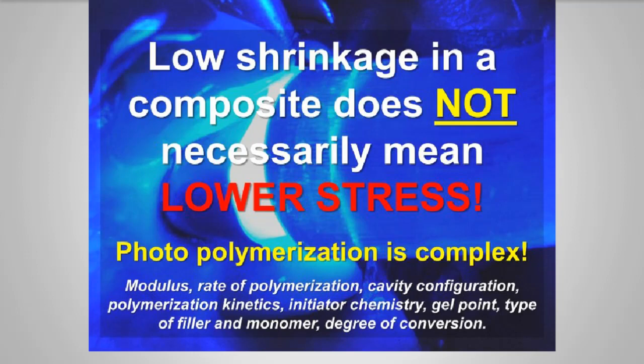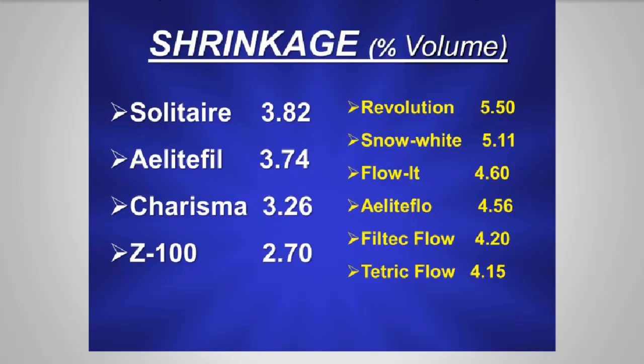As a very quick example, we can look at some composite materials here. These are all flowables in yellow on the right, and more heavily filled composite materials here on the left. And if you were all here, I would ask you a question. That question would be, why do flowables generally shrink more than their more heavily filled cousins? And the answer, of course, is they have more resin content relative to the more heavily filled materials. And it's the resin that actually does the shrinking. The filler particles don't shrink. It's the resin that actually shrinks. So all other things being equal, the more resin in a composite, the more shrinkage is a factor.